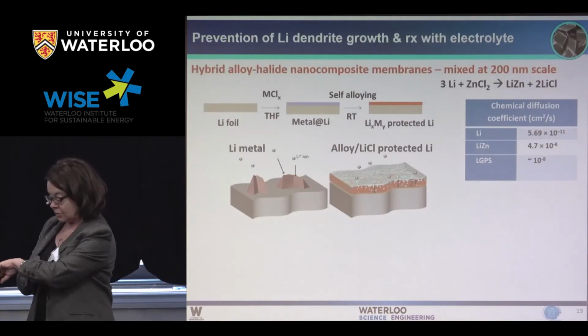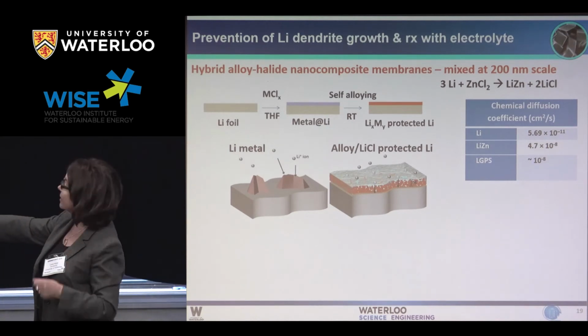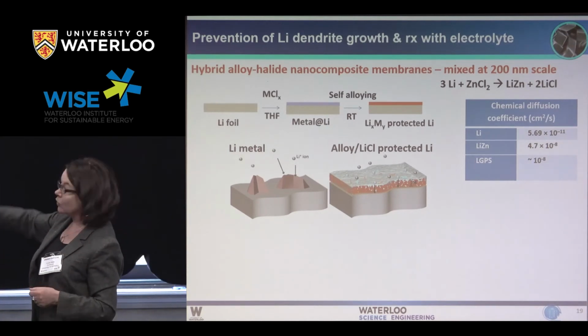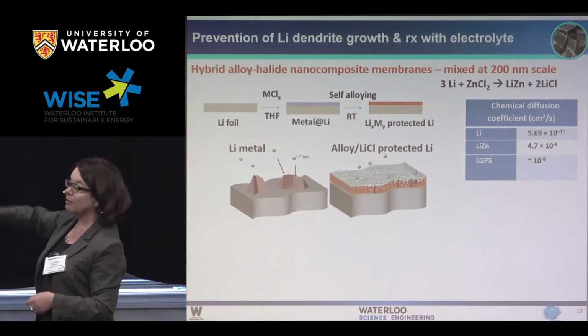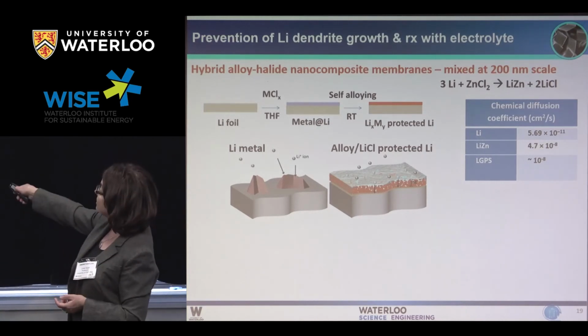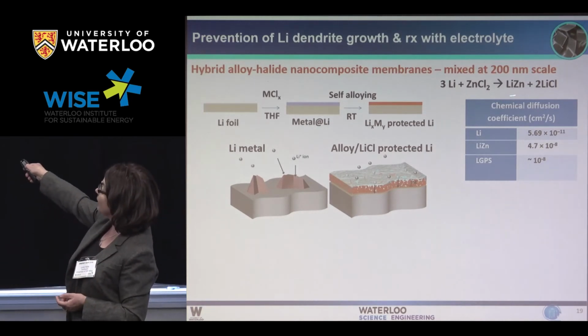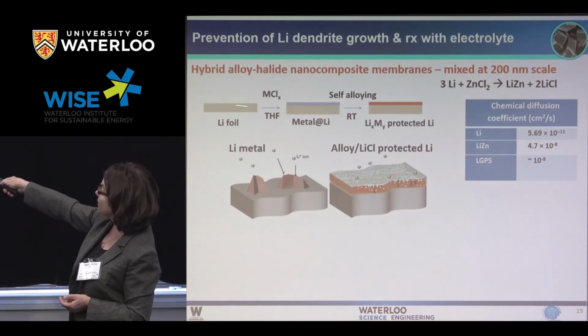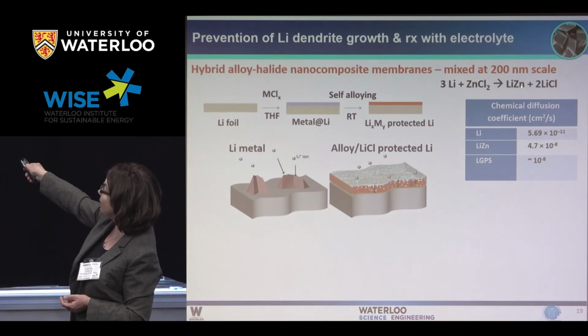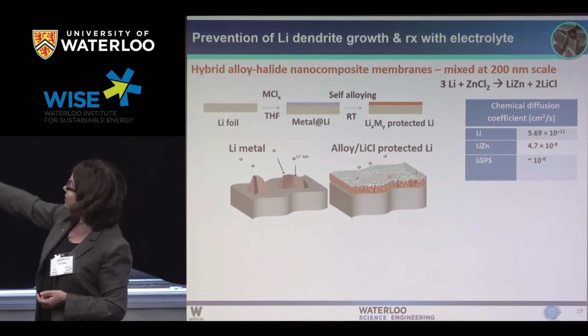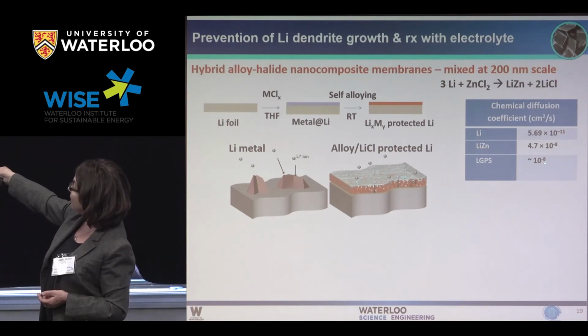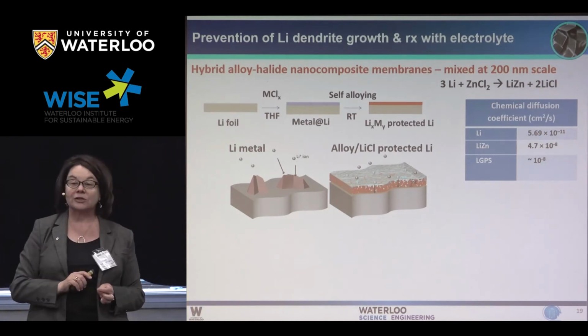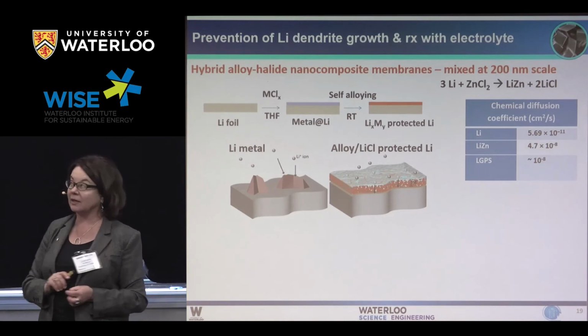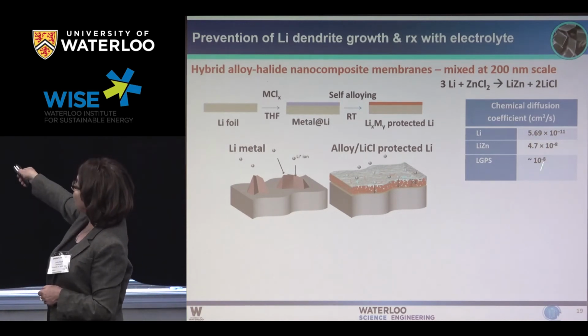We've developed two kinds of materials, two slides, that's it. And we're looking at scalable methods of making these, as opposed to very expensive things. So for example, we've developed really simple chemistry where we simply treat the surface of lithium foil with a metal halide, and it produces what's called an alloy, which kind of self-forms on the surface. And these alloys actually have a diffusion coefficient that's very similar to that material that I just told you about, the LGPS, that solid-state ion conductor. They're in the same ballpark.